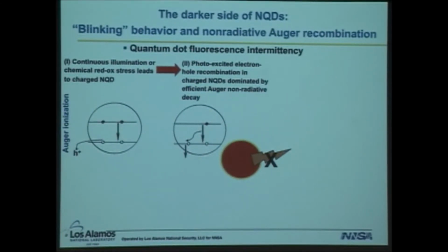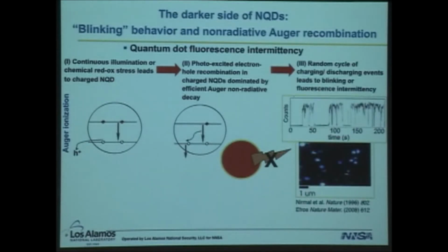So if you generate with light another electron hole pair, the energy of recombination of that electron hole pair would ideally go into emitting a photon, but instead it's transferred to the third carrier, and it could be a hole, as I show here, or an electron. And that third carrier basically gets bumped up in energy and then decays and loses that energy non-radiatively as heat. And so therefore, a charged quantum dot in this traditional model of fluorescence intermittency is a dark quantum dot. And therefore, it has long been thought that blinking results from a random cycle of charging and discharging events in the presence of an active Auger process.